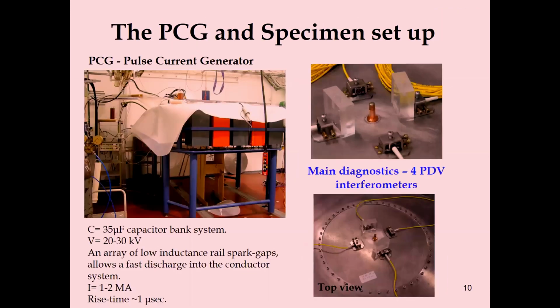So this is just the pulse current generator we're using at Rafael. We have a capacitor bank system. We're charging up to about 30 kilovolts. We're getting 1 to 2 megaamperes, and the characteristic rise time is about 1 microsecond. And that's the most important number here, because that's the number that will characterize which strain rates we could reach. So theoretically, we're going to see that we could reach up to 10 to the 6 because of this very high rate. So here on the right, you could see one of the specimens as it's mounted on the pulse current generator. We have 4 PDVs.